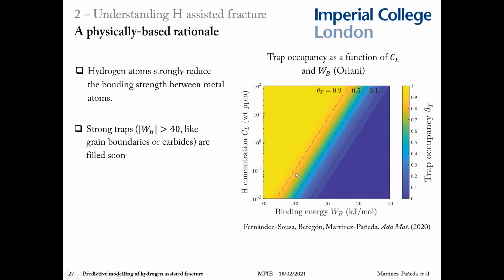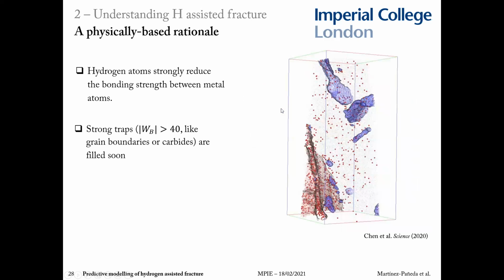So if you go here in this graph, you will see that as long as you reach any meaningful value of the lattice hydrogen concentration, it will give you a full occupancy of the trap, or almost full occupancy of the trap. And this is what you see in experiments. So this image is taken from a recent atom probe tomography study. And you can see how this grain boundary, the red region, is full of hydrogen atoms. So our grain boundaries are definitely going to be weaker.